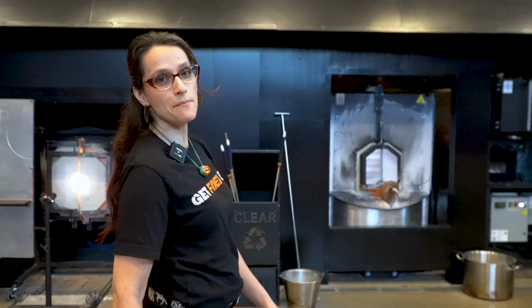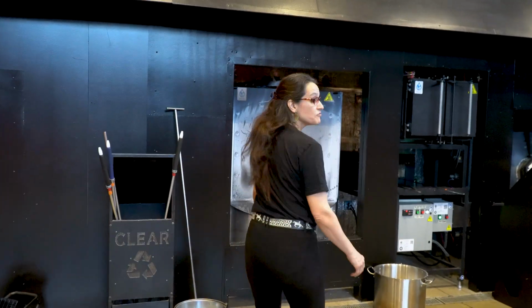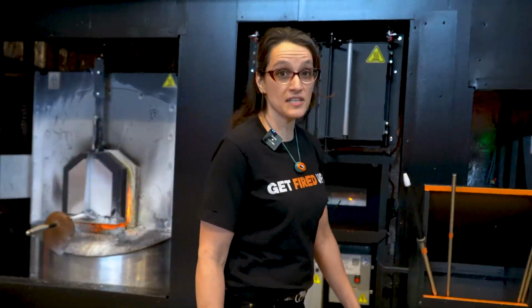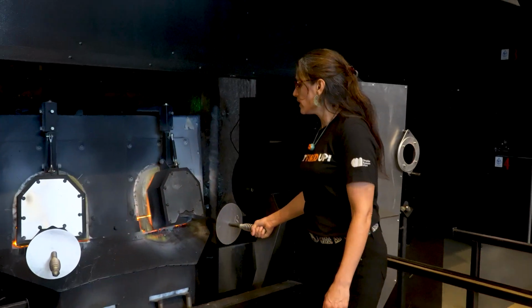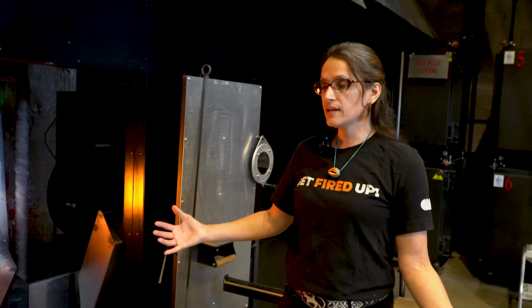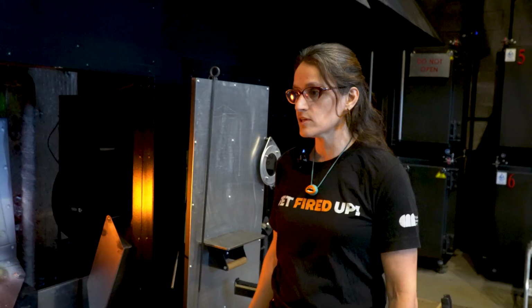In our Meredith Amphitheater shop, we have a furnace full of molten glass. This is 560 pounds in this shop, and it's at 2,150 degrees. So this is where we do glass blowing. In this shop, we also have color pots. So this is a rare treat where we melt color straight in these furnaces instead of clear like you usually have, adding the color separately. We can just pull hot, molten color right out of the furnace.